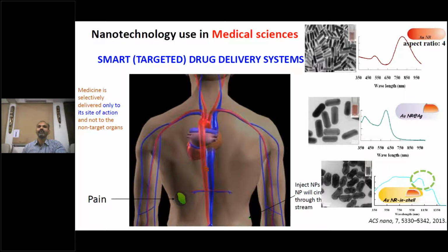What we did, we took these gold nanorods and put them in silver with citrate, and we were able to see that silver growth. You can see here an intense gold core and a little less intense silver shell, and this gold core silver shell was again sunk into gold solution. Since, as I mentioned before, gold is highly noble, it tries to capture electrons from anywhere, right? So it starts taking electrons from the silver and starts depositing on the surface. The silver ions on the surface of this gold start leaching out, and the gold starts building over, and then we get a shell.